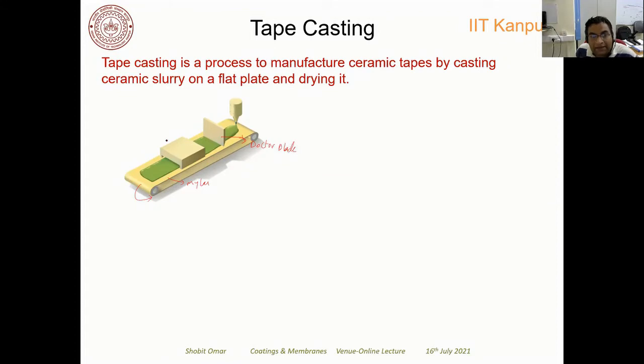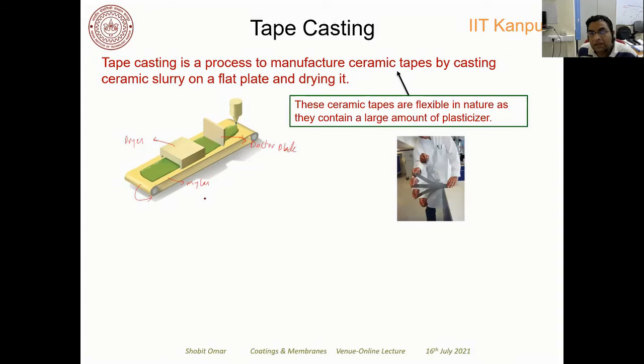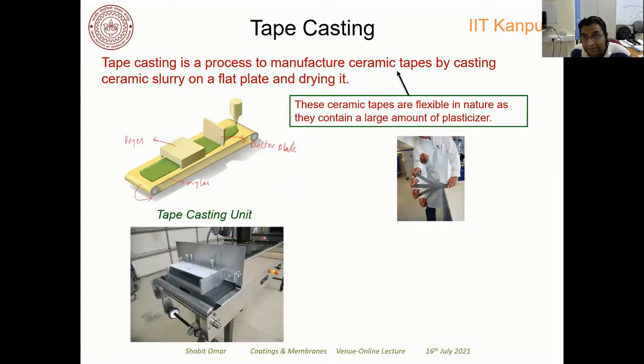Okay, and this is the dryer which is present to dry the coating. So you can get a flexible ceramic tape out of the tape casting technique, right? So you see how flexible these ceramic tapes are, and this flexibility you get from adding the plasticizer inside the slurry. We normally know how brittle ceramics are in nature, right? They are very brittle, but you can provide the flexibility by adding a plasticizer and other additives.